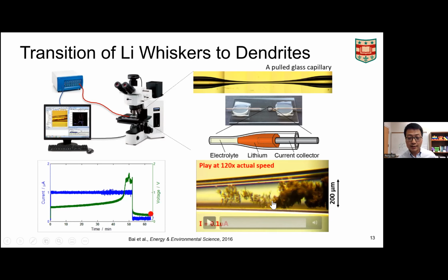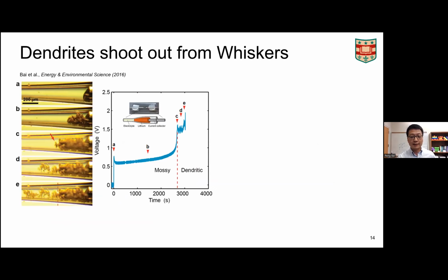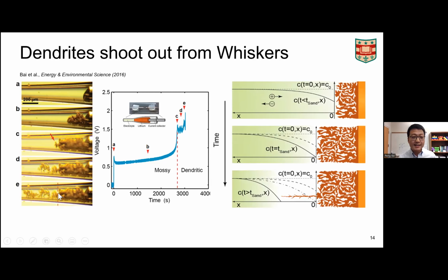And this kind of transition point is also revealed by this sudden change of the voltage indicated by the green spike over here. And this is where we have the fundamental science coming, that you need to consider what is going on in the system, right? We can see the morphological change, but what we can't see by naked eye is that there is a concentration change in the liquid phase, in the electrolyte, okay? And then you have to solve the diffusion equation to get a characteristic time that is called Sand's time. It's not because of the sand we are playing around with, it's because a pioneer called Henry Sand derived this equation more than 120 years ago. And that theory was applied to our battery research nowadays.